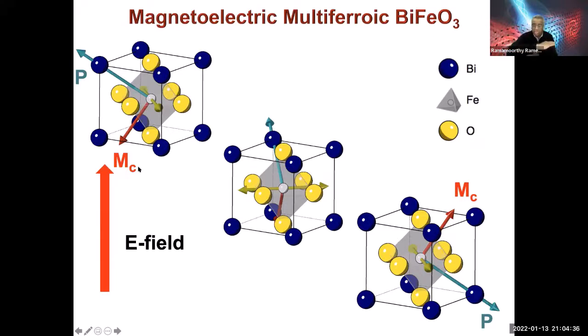Instead, the polarization is rotating very much like a ferromagnet. By the way, that by itself was very provocative, very troublesome for many people like myself who had been immersed both in ferroelectricity and magnetism. In magnetism, of course, the spin is immutable, so you rotate the spins. But in ferroelectricity, we were taught that the dipole moment can mutate, and therefore it can reduce to zero and then switch. But BFO was behaving very much like a ferromagnet.